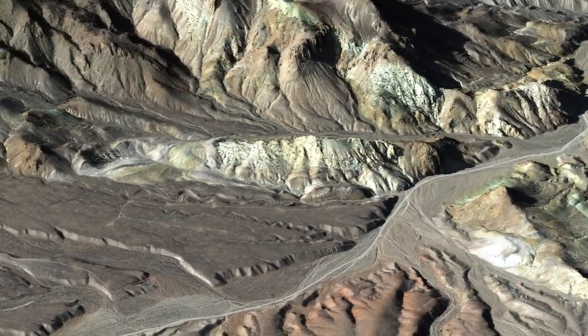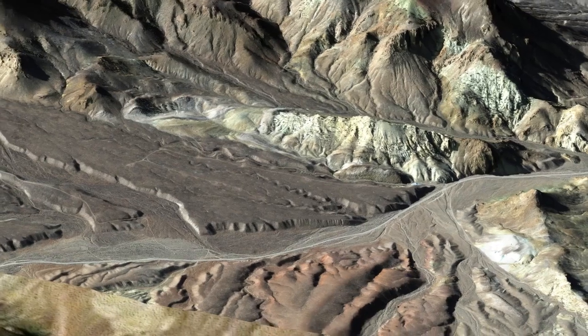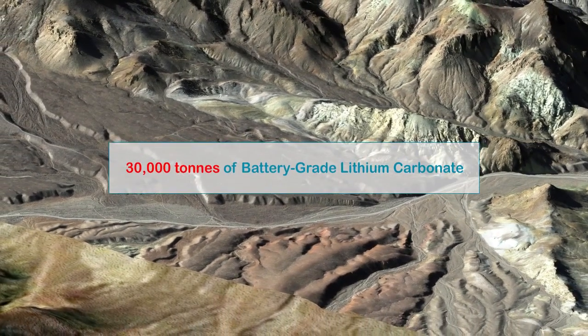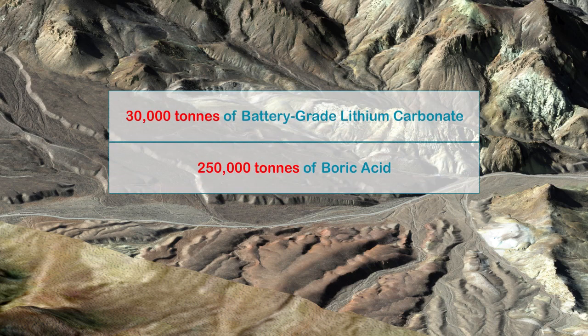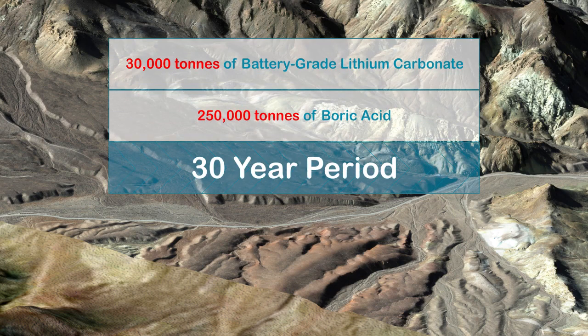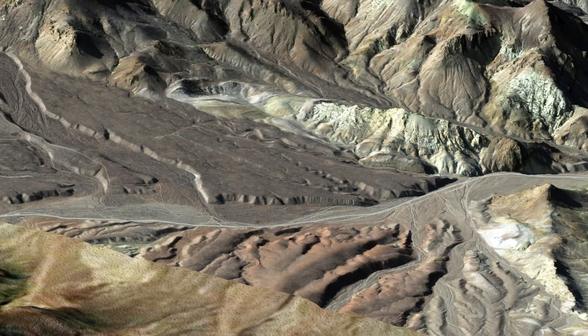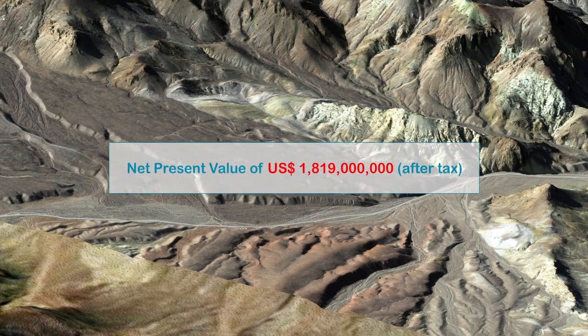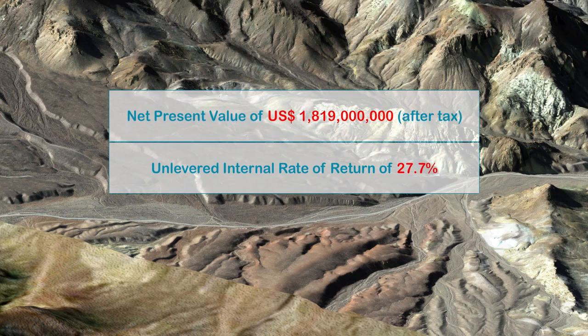Based on the current resource estimate, Rhyolite Ridge can produce up to 30,000 tons of battery-grade lithium carbonate and 250,000 tons of boric acid per year over a 30-year period, making it one of the larger lithium and boron mines globally. Our pre-feasibility study has demonstrated the very strong economics of the project, with a net present value of $1,819 million after tax and an unlevered internal rate of return of 27.7%.